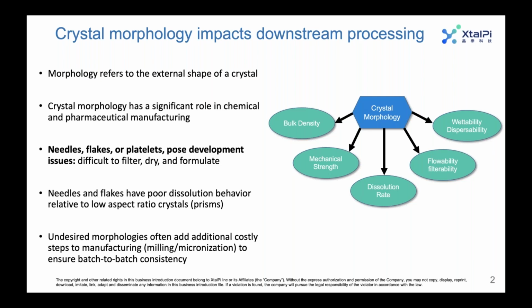Specifically, needles, flakes, or platelets can pose development issues because they're difficult to filter, dry, and formulate. Needles and flakes also have poor dissolution behavior relative to lower aspect ratio crystals like prisms. So we definitely prefer prisms, but oftentimes we're stuck with needles or flakes. And these undesired morphologies often add additional costly steps to manufacturing that are used to ensure batch-to-batch consistency. Specifically, techniques like milling or micronization are used to deal with these types of morphologies.